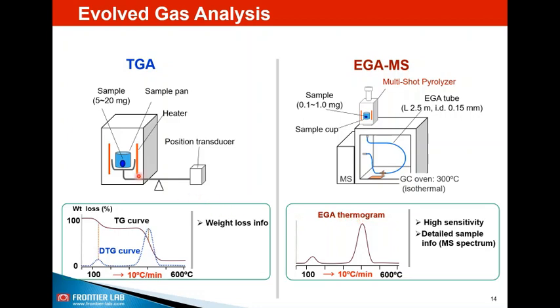You are heating the sample from a start temperature to the end temperature at a given ramp rate, and you are collecting the weight loss information. Then using this data, you can generate the temperature profile of the material by using differential thermogravimetry. What you get is the maximum peak height for the additive group and polymer group. So this basically tells you the temperature profile of the material. You can get similar information and extra information if you are using evolved gas analysis.